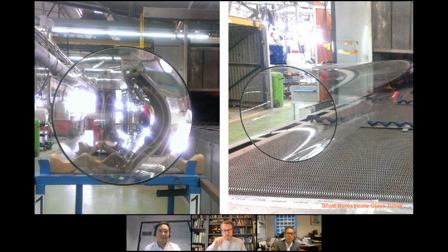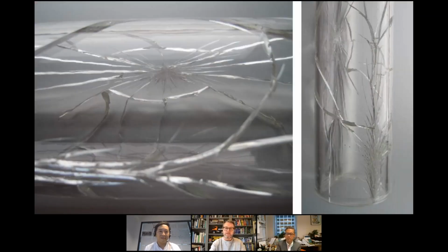So here is one of those 400mm diameter tubes, rather beautiful in itself in its circular nature, again 3 meters long, coming out of its furnace. And this is an illustration of what happens with some of our experimentations when we started to try and laminate them. When you put the tube within a tube, or even two half diameters around a tube on that scale, the shrinkage within the interlayer and the imperfections between the two surfaces caused an awful lot of cracking in the process.